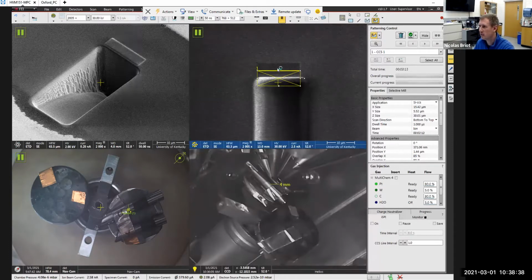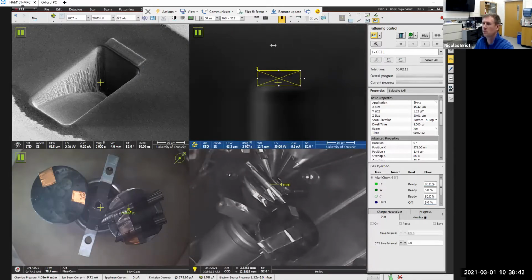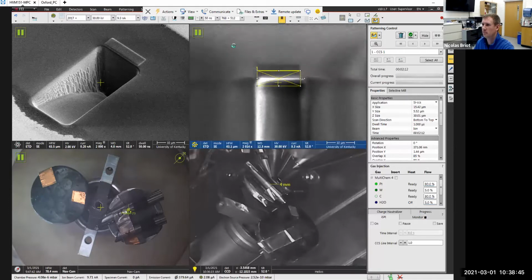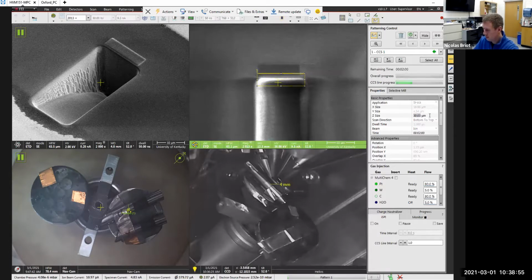It takes a bit of time, so let's see if I can go a bit faster. Something like that. There we go. 5 microns. What time is it? Okay, we have time to do the thing. And hopefully we went deep enough, or at least we can get the signal from deep enough, because it's nice to open that little trench, but we want to be able to place the SEM electron beam all the way to the bottom of that pit, but we also need to be able to get the X-rays out of it without them being shadowed by the side edges of the trench, that sort of thing.